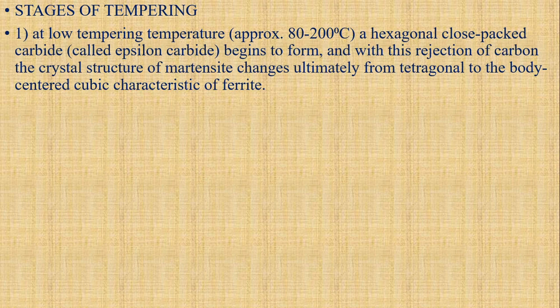Stages of tempering. At low tempering temperature, approximately 80 to 200 degrees Celsius, a hexagonal close packed carbide called epsilon carbide begins to form, and with this rejection of carbon, the crystal structure of martensite changes ultimately from tetragonal to the body centered cubic characteristic of ferrite.